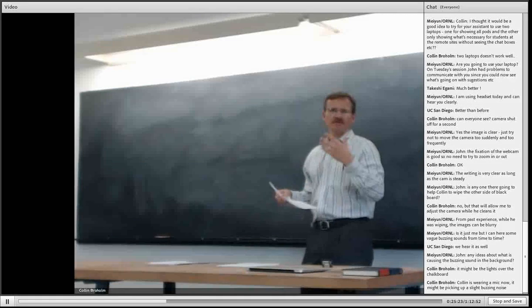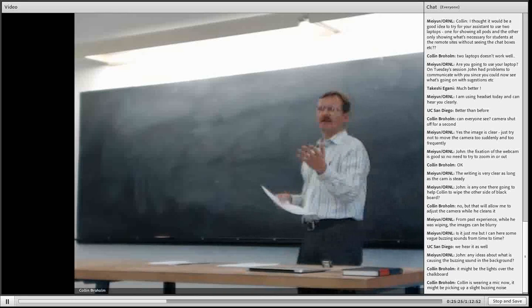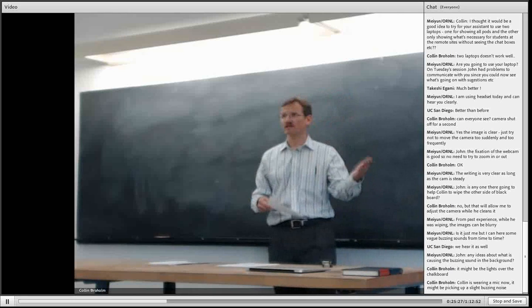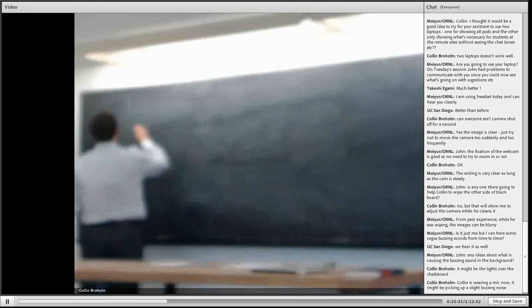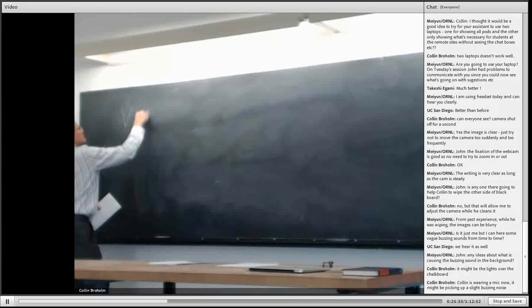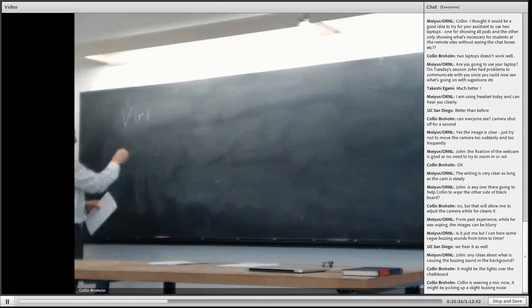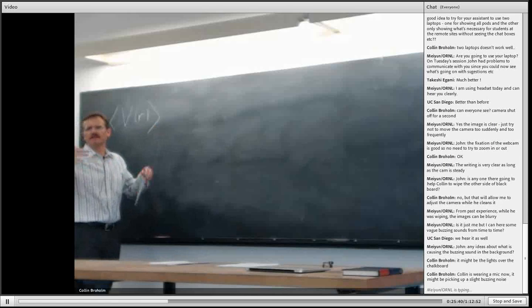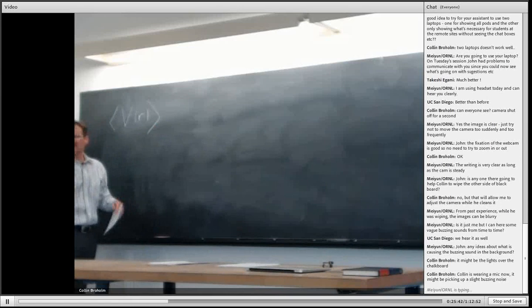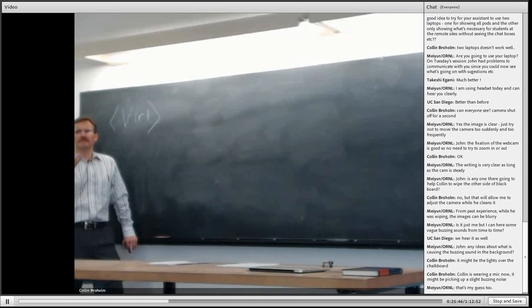This brings me into the limit of something like an electromagnetic description of the interaction between the neutron and the material. What then happens is that the potential I'm going to be dealing with is the average of the potential over a sufficiently long length scale, but not too long, because then I'll lose all of the detail of the interfaces between the materials that I'm dealing with.